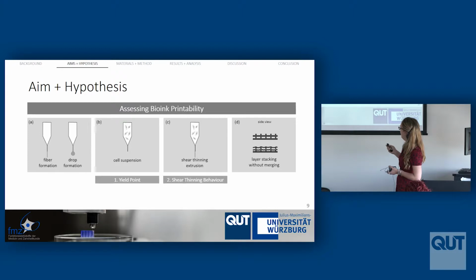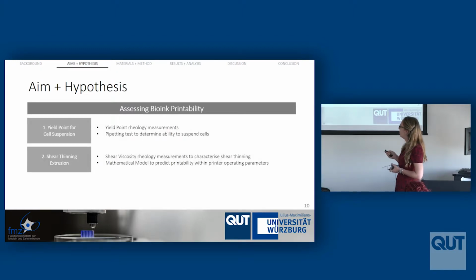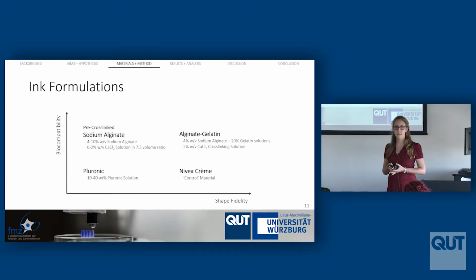And so this is just summarizing these, our yield point for cell suspension. And so we use our rheology measurements, which I'll show you in a minute, and then also our shear viscosity. So looking at how the material changes as you apply new forces to them to make sure that overall our material will be printable. I used a lot of different ink formulations, and so these ones are all very popular in the literature and are used by a lot of different groups for different applications. And they range in shape fidelity, so this is how well we're able to make some really beautiful constructs out of them, and also biocompatibility. So firstly, I used Pluronic, which is a synthetic polymer.